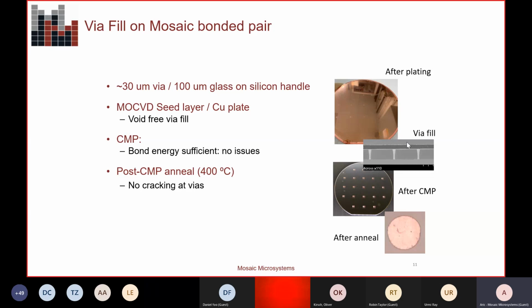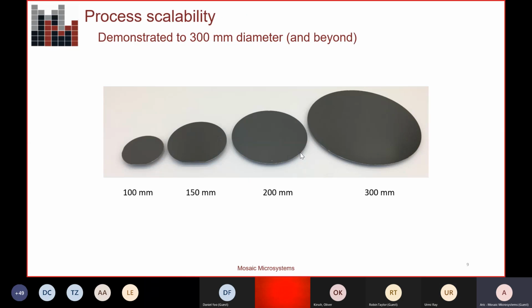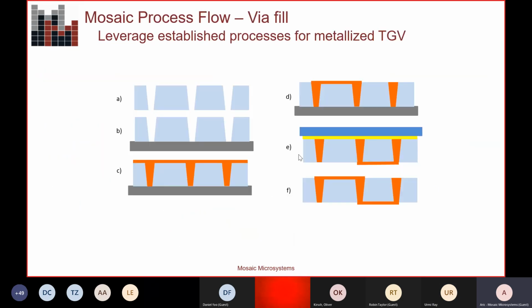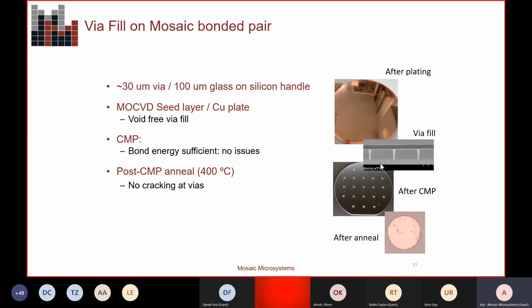So after CMP, it's generally less than 1 nanometer is what we've been specifying, and that hasn't been an issue. Along the sidewalls, I don't have a good measurement of the roughness, but it's a very smooth via. You can get some idea from these profiles. I don't know that it's sub-nanometer, but it's very smooth. It's not rough like a PCB type via would be. I don't know if I have a better image, but this gives some idea of the smoothness. That's maybe something we could take a closer look at if it's important. But it is certainly sub-micron.